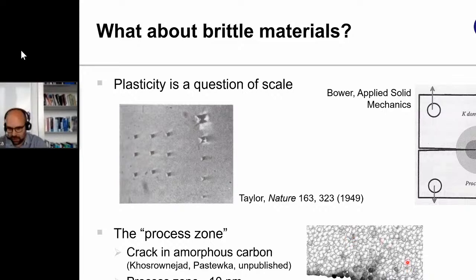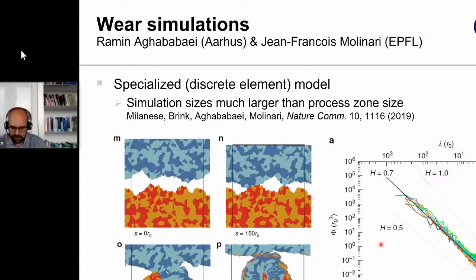Here the color indicates the change of coordination number of the atoms near the crack tip, where we can say something about fracture. This is, of course, aside from brittle crystals; silicon and diamond are perfectly brittle. So you have to do something else, and this leads me to some beautiful calculations out of the group of Ramin Aghababaei, who is now at Aarhus, and Jean-François Molinari at EPFL, who used a specialized model. They call it molecular dynamics. I would probably call it a discrete element model. Sorry, Jean-François, if I'm deviating from your nomenclature.